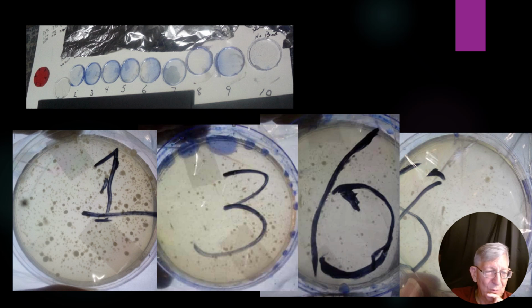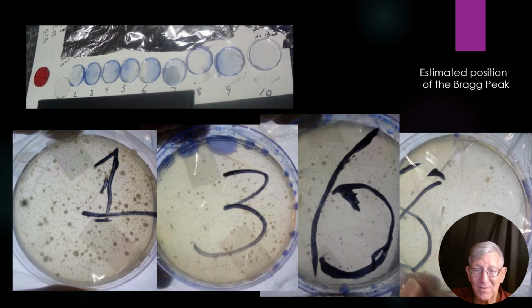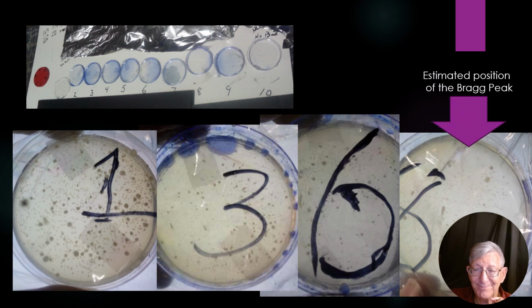And we see the same thing in 3. You see fewer colonies, and you see a similar asymmetry of the colonies. If you go down to 6, you have the same asymmetry, and you have fewer colonies. And if you go down to 8, there's almost no colonies at all. And 8 is about where we would expect to see the Bragg peak for all of these. This is the estimated position of the Bragg peak. Bam. And guess what? We are seeing something: the radiation is killing off the bacteria before they can multiply.